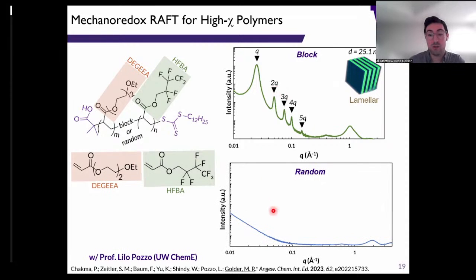This is in stark contrast to when you make a statistically random copolymer by adding all of the monomer in at once, right? So I add the hydrophilic monomer and the fluorinated monomer to the same jar, and I mill for a few hours. I would expect a random copolymer that doesn't show any self-assembly on the nanoscale. So this demonstrates that we're not getting two types of homopolymers that are mechanochemically cleaving and coming back together at random. We really have good control over sequence here, and mechanochemical chain scission seems to be a very minor component of this process, if it exists at all.